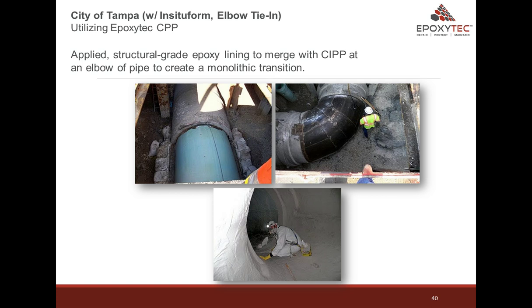Structural epoxies can be used in conjunction with CIPP and other lining solutions. This is the City of Tampa with Insituform, elbow tie-in utilizing Epoxytec CPP, applied structural grade epoxy lining to merge with CIPP at an elbow of the pipe to create a monolithic transition.